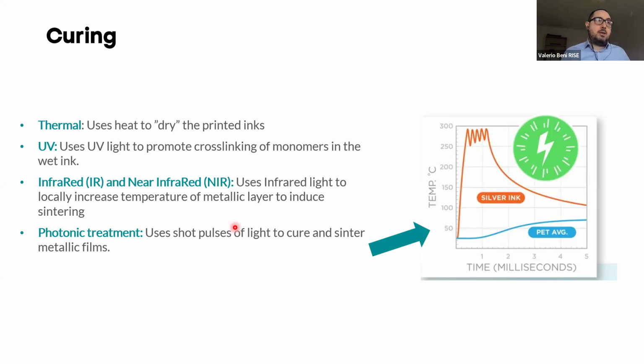This is the most common one, but there are also a lot of other curing processes that are under development or more exploratory. The most common is the thermal curing, where you simply evaporate and dry out the solvent and dry out the inks. You have UV curing, mainly used for dielectric materials, where you use UV light to cross-link monomers or molecules inside the inks so that you create nice and uniform films.